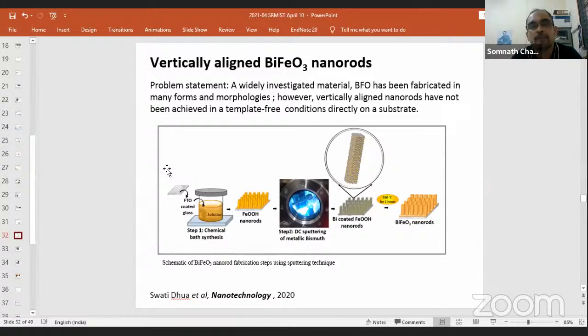So she found out from literature that bismuth ferrite has been prepared in many forms: thin films, single crystal, polycrystalline powder. But no one had actually succeeded in preparing bismuth ferrite in nanorod form. There was, of course, a paper not so far from here, I think from Coimbatore or Madurai. I think Coimbatore. They had prepared it, but their nanorods were extremely short, very short. And there is another group who had prepared it using a template-assisted method.